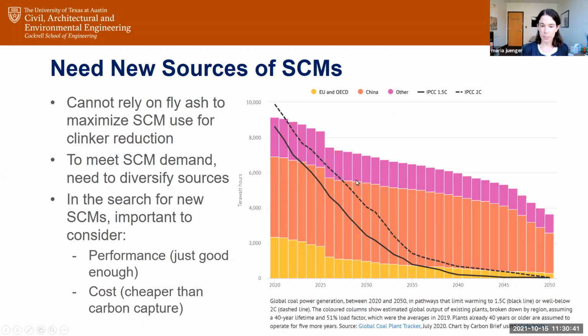Historically, in the US in particular, fly ash met all of those criteria. So fly ash is a byproduct from burning coal for power. It was an amorphous material, mostly glassy, high in silica and alumina. It already came as a fine powder, you didn't need to grind it. It was a byproduct from another industry, so in terms of embodied CO2 and embodied energy, it was doing pretty well.